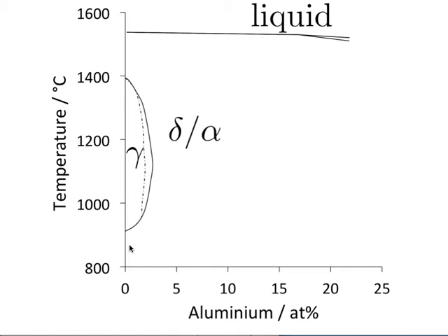Okay, so we're going to use a different concept now. Instead of allotriomorphic ferrite, we are going to retain some of the delta ferrite, which forms directly from solidification. So the structure will look completely different, all right? Because, you know, what is the shape of a crystal which forms from liquid typically? Dendritic.